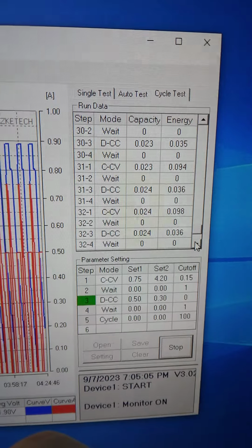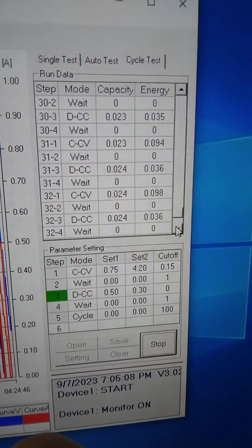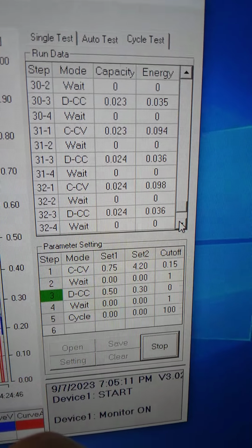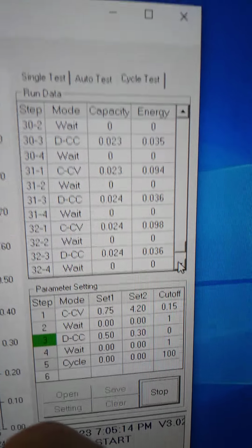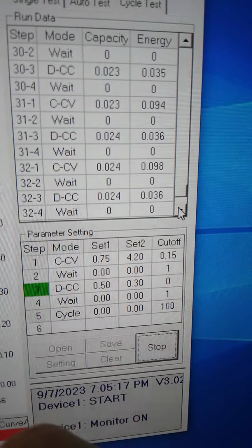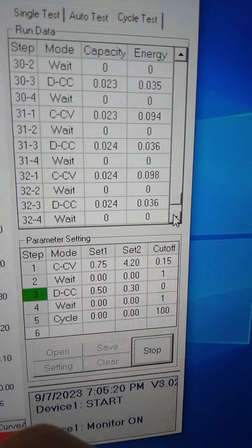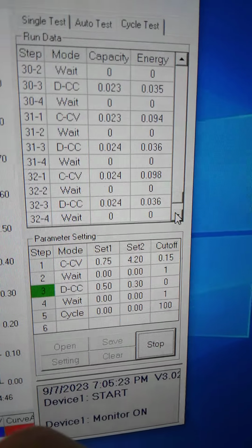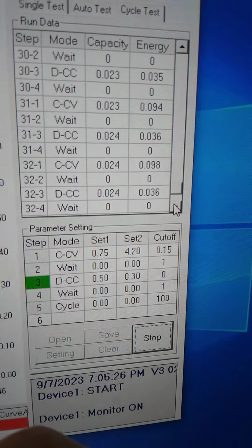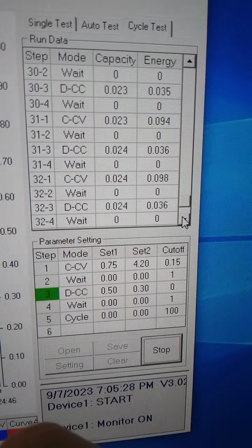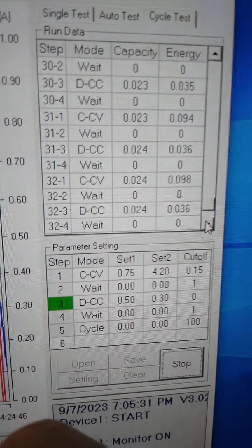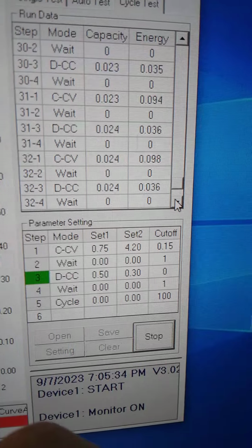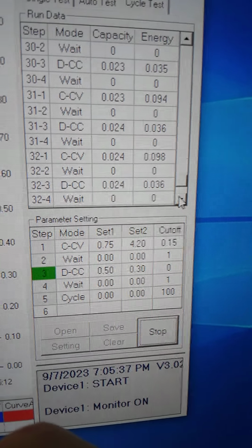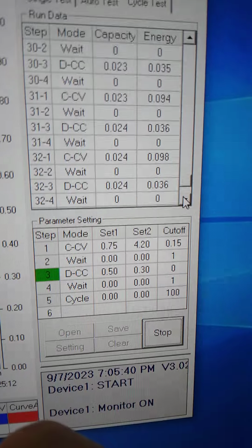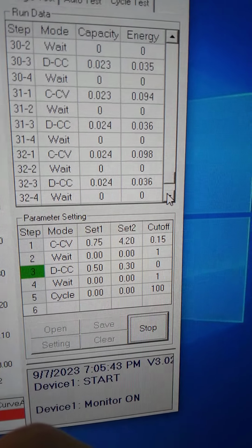And right now, very interesting, I've seen this before. It'll start off with a Coulombic ratio, and I estimate that by looking at the capacities, milliamp hours for both charge and discharge. You can see they're pretty steady. They start out about 0.024. And then at about cycle number 15, it goes down from 0.024 down to about 0.023. And when you hit cycle 31 there, it's starting to go up a tiny bit again, 0.024. But I'm looking at the ratios, and I want 1-to-1, and I'm getting it, which means I'm not losing energy as thermal, as heat.